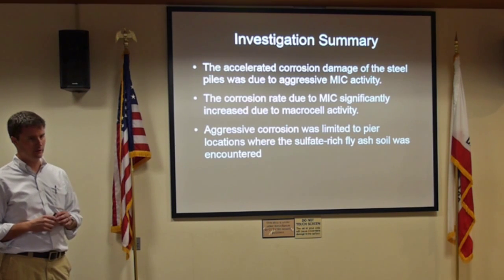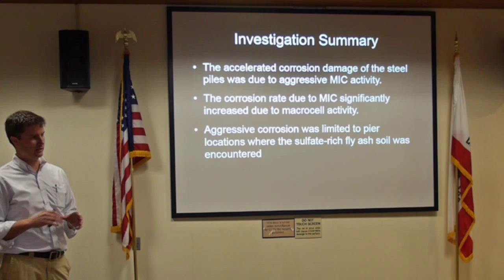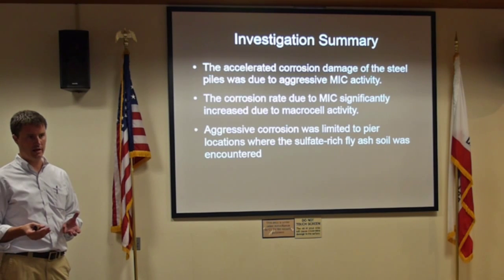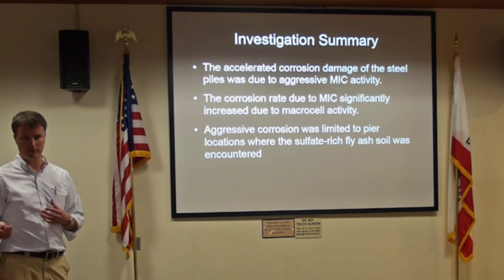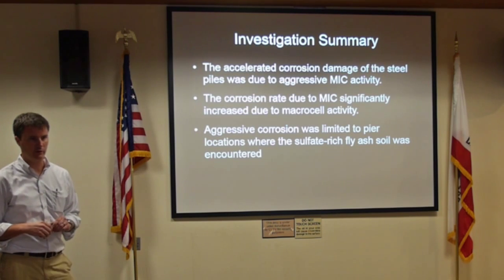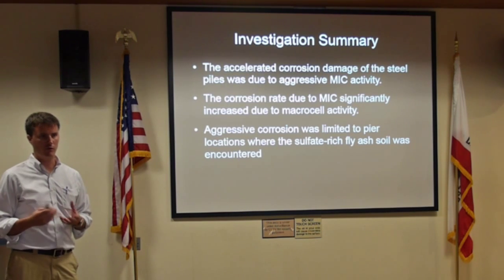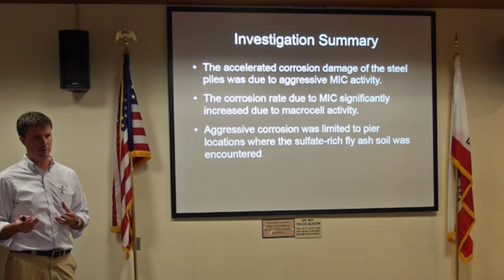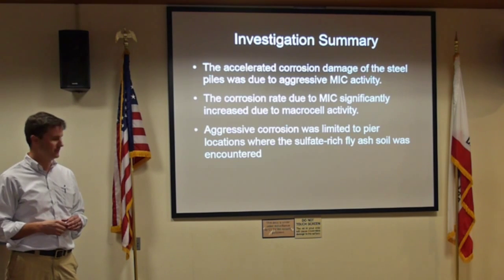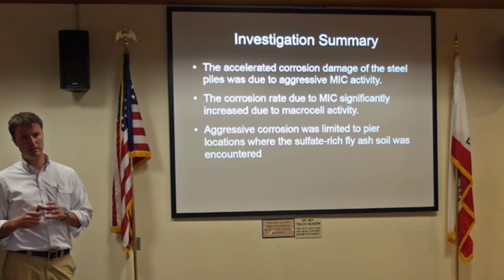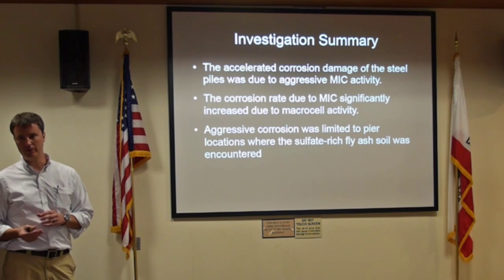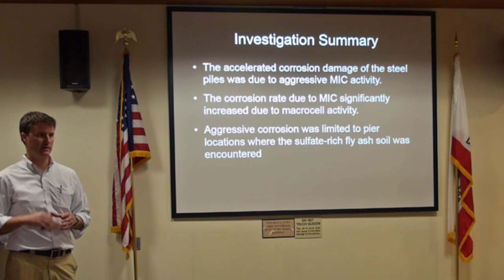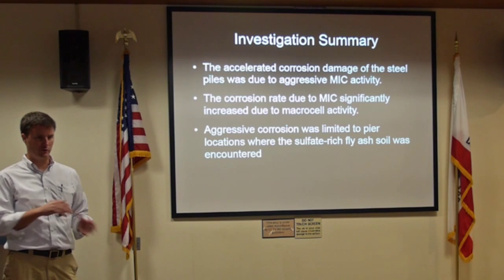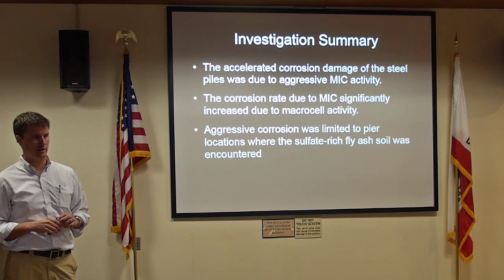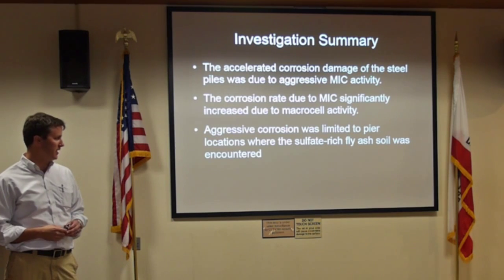And what we found to be the only factor is that this area had been filled with fly ash heavy material, given some of the industry in the area, and that created a very conducive environment for these microbes. That's where you have the most aggressive corrosion. In other areas where they had clays, you didn't have the correct environment for this, and with the rivers adjacent to this area, the transfer of water through those clays was okay.